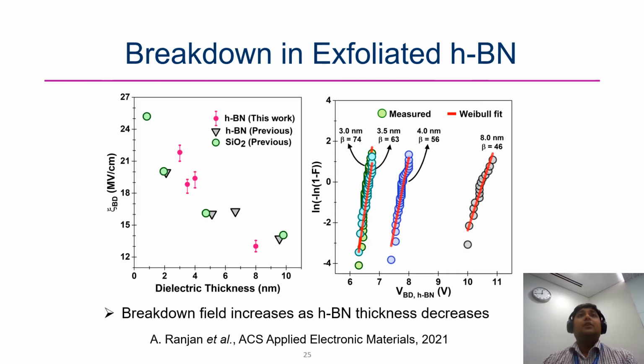So finally, we also investigated the breakdown field strength in the high quality hexagonal boron nitride, and we found that the breakdown field strength increases as the thickness is decreased, and this is in accordance with other conventional high quality materials, for example SiO2. Another aspect we found is that the values of the breakdown field are also comparable to industry quality SiO2, which also tells us that it's a robust material which can be reliably integrated from the breakdown perspective.